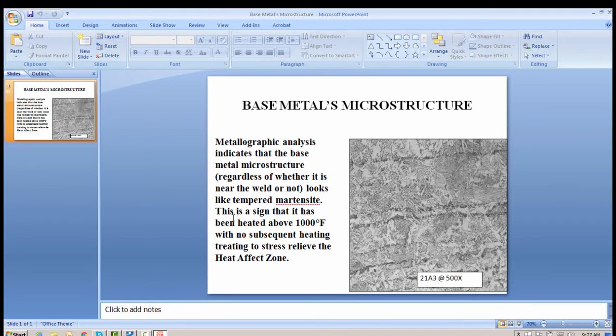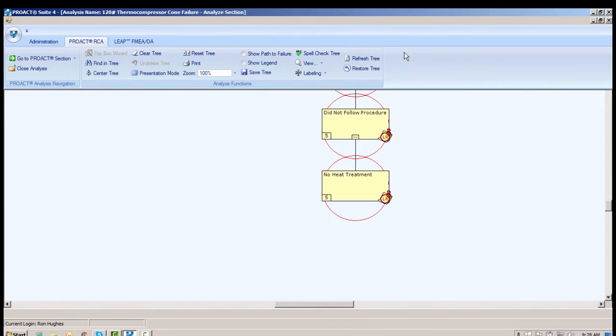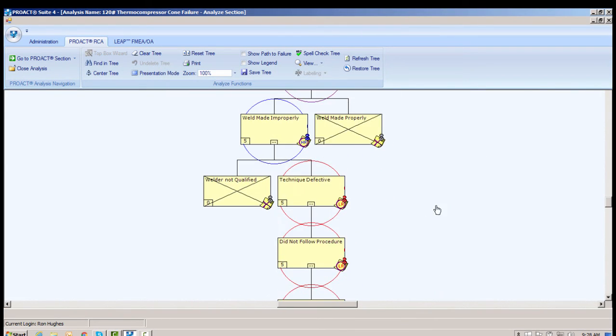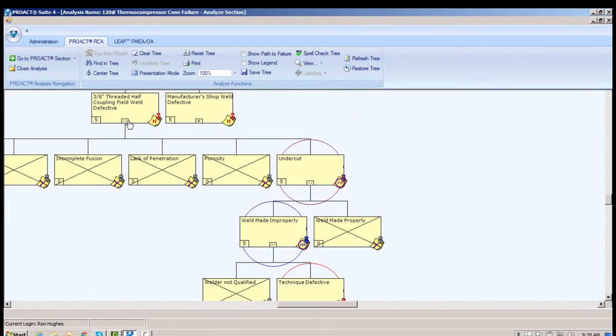We actually did put the material in a X-ray analyzer to see what it was, and we found, and we're going to find, that it's actually the wrong material for the service. But here when we look at it, metallographic analysis indicates that the base metal microstructure, regardless of whether it's near the weld or not, looks like tempered martensite. And like I said before, this is a sign it's been heated above 1,000 degrees Fahrenheit with no subsequent heat treating to stress relieve the heat affected zone. So that answers that, and that takes care of the field weld.